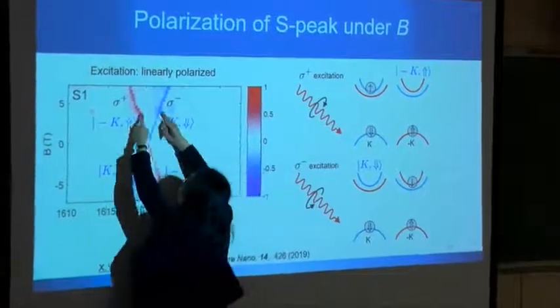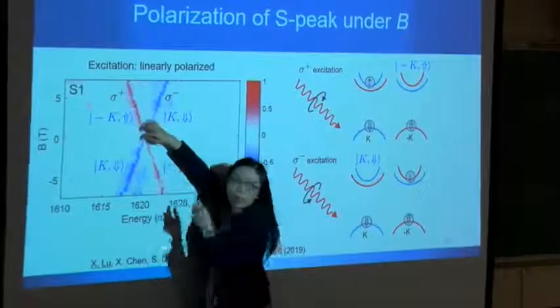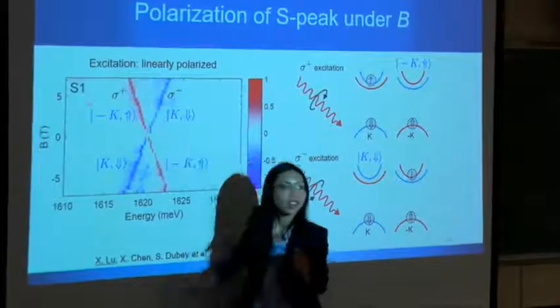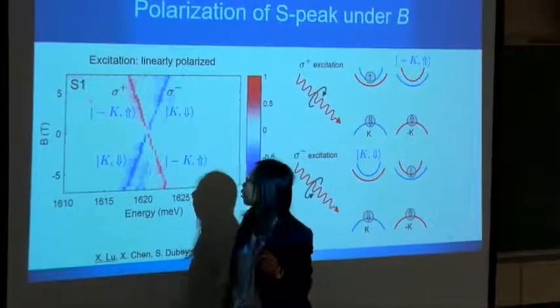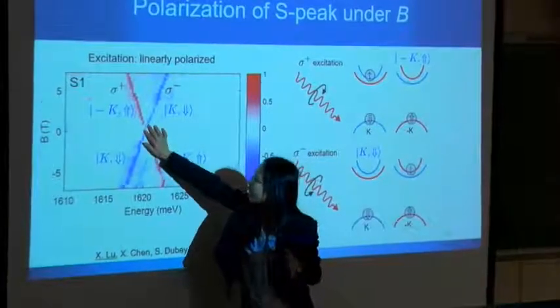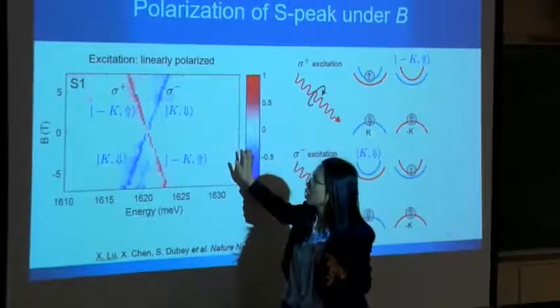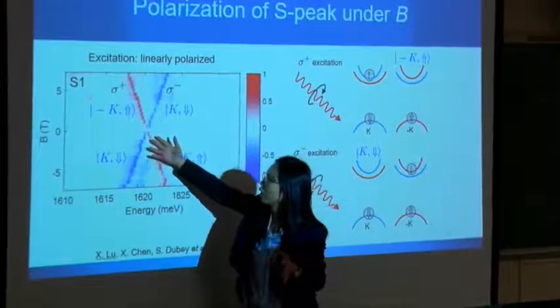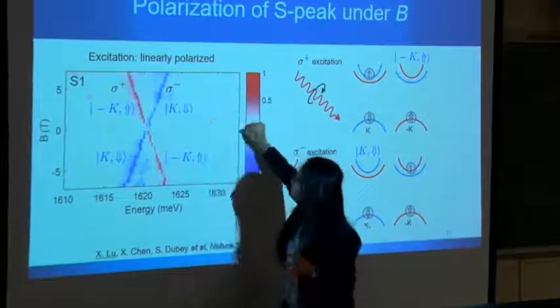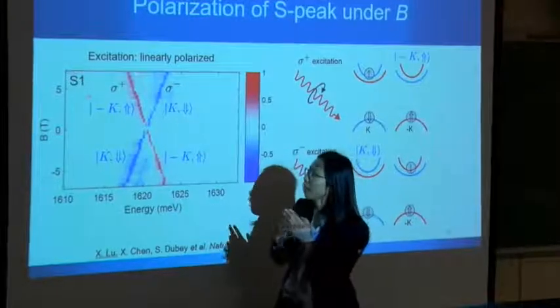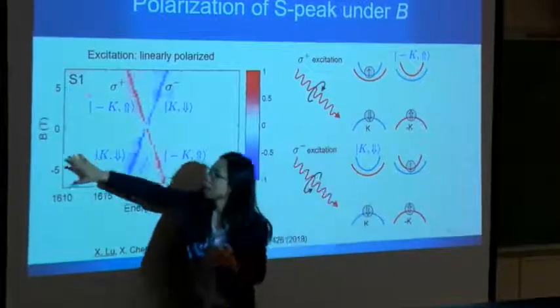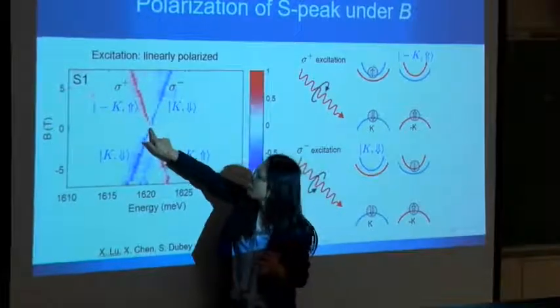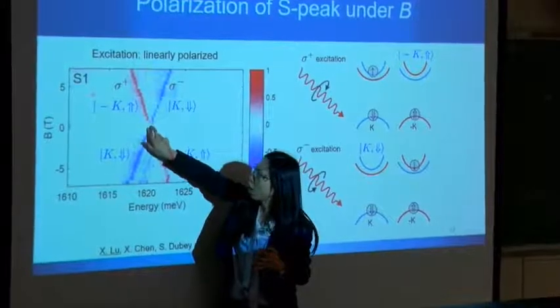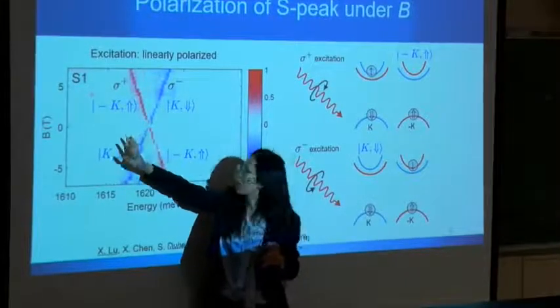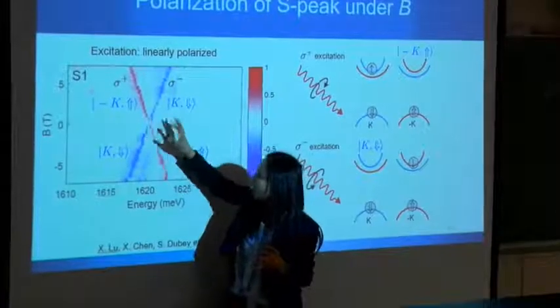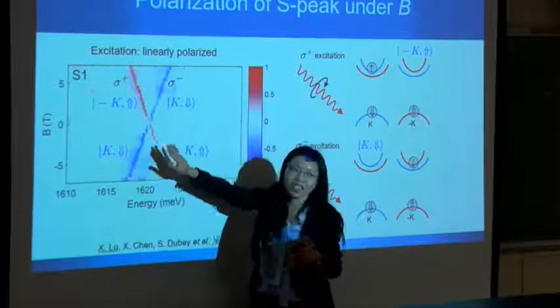So are you thinking that probably this is like a parabolic dispersion, and then we have a small gap here? Yeah, you have a small gap. In fact, from this presentation, from this scale here, it looks like a small gap. But I think it's probably because we are plotting it in a polarization basis, and I scaled it a little bit. If I plot it in intensity, you will not see it. It is a little bit broad, this peak is around 200 micro electron volt. I do admit that it looks like a gap, but it is actually not.